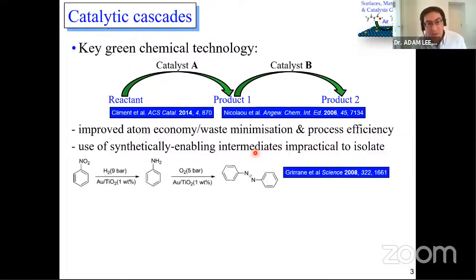A couple of examples here. First of all, of a reduction and then an oxidative coupling of, in this case, nitrobenzene. And here's an example where catalyst A and B are the same. Both are gold titania. And so this catalyst in one reaction vessel can do a reduction using hydrogen and then an oxidative coupling using oxygen to make our coupled product here.